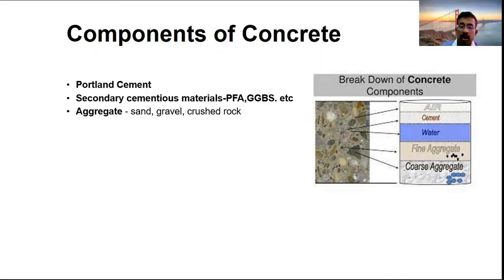So Portland cement, what kind of cement we are going to select is very important while making concrete. Whether a pure OPC cement or a blended cement, slag cement, high volume slag cement, high volume fly ash cement. So many types of cements are available in the market. If you are making site mix concrete, going with a blended cement is the most ideal thing. As I already told you, using OPC is detrimental to concrete. Not only detrimental to concrete because of the various reactions, you are also increasing the carbon footprint, as the emissions are more using OPC cement.